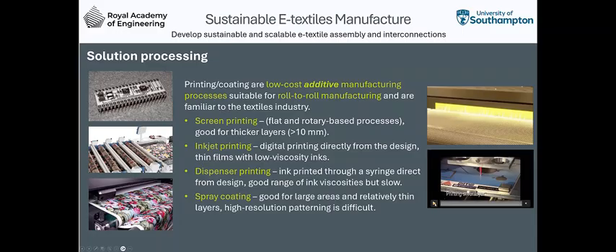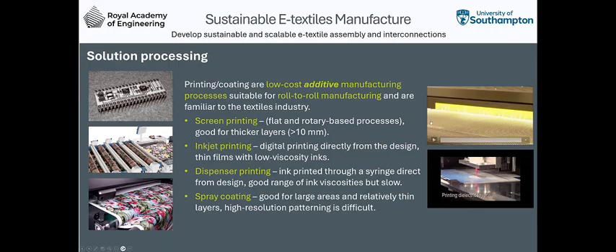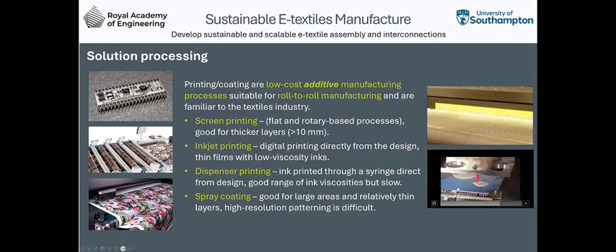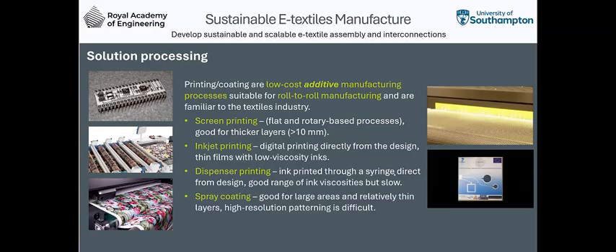The other printing process we use is a dispenser printing process here, where the same sort of ink is placed inside a pneumatically driven syringe, and you can print any design directly from the PC onto the textile. So the screen printing relies on a screen which has to be designed and sent off and manufactured, etc. In this case, we can go directly from that design straight onto the textile. This is just showing an example of an electroluminescent device. By building up the printed layers, you can build up a device. The downside of this process is it is a little bit slow. So it's great for prototyping, but you wouldn't use it for mass production. And this finally shows the electroluminescent device lighting up.